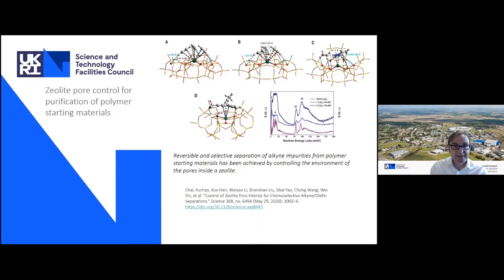So there's a chemoselective binding, and I apologize, you can't see the numbers here, but they have this absolute determination of the loading of acetylene, ethylene, etc. on these systems. So not only can we say where these molecules are binding, but we can also talk about the dynamics. And this is what's shown here. This is some inelastic neutron scattering, which compares the solid acetylene with the acetylene that's bound to the nickel sites. And you can start to see all of the changes to the translational, librational, vibrational modes in the structure. So not only do you have this determination of the structure, you also understand how these atoms are moving around.